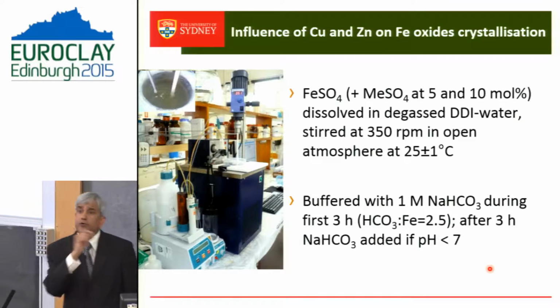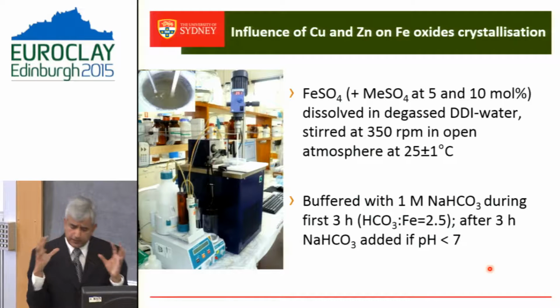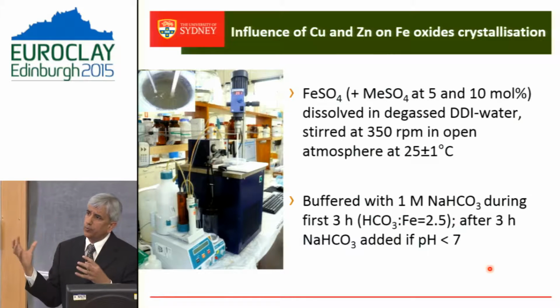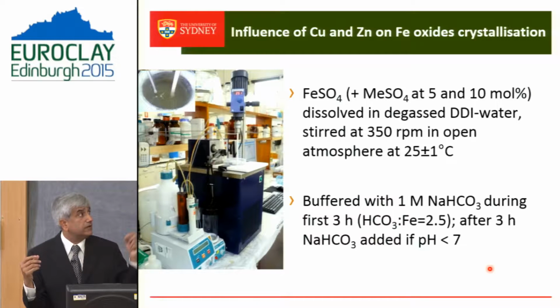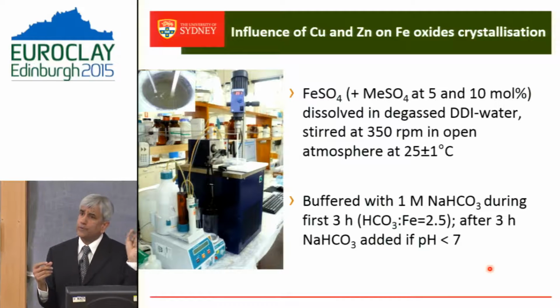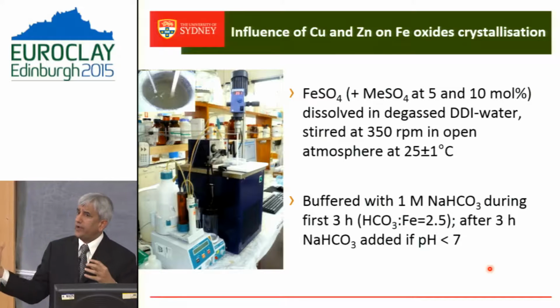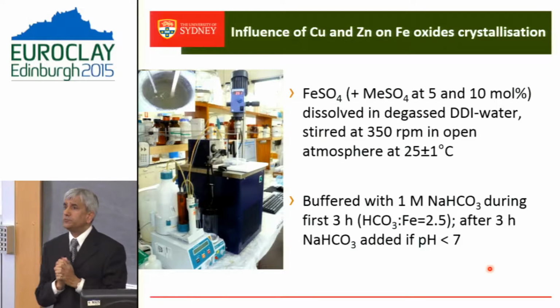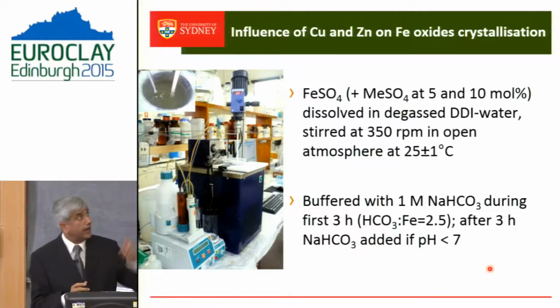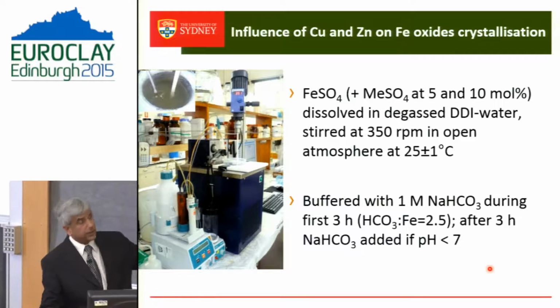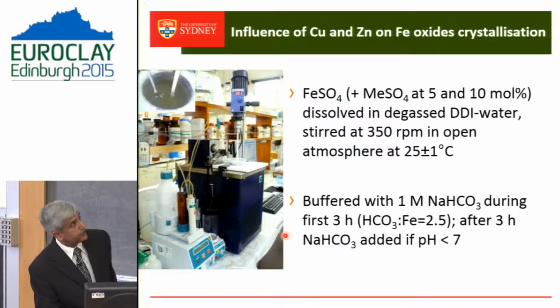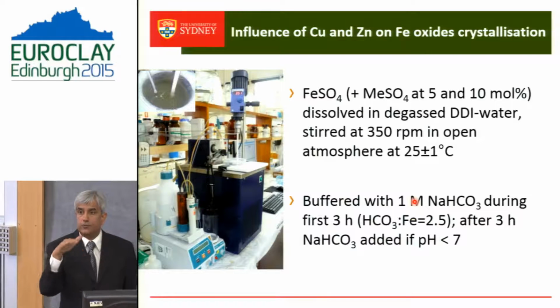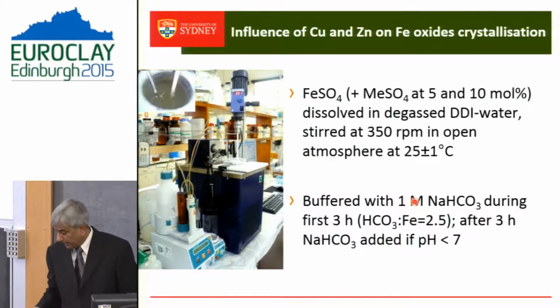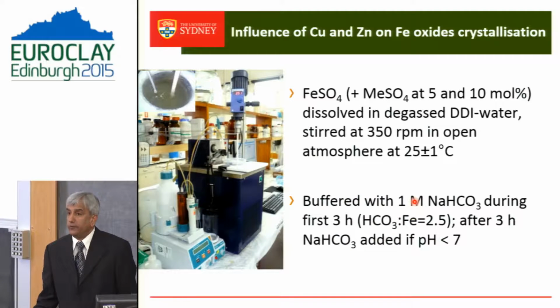One more example I want to give. We have seen that all these metals can get incorporated in the structure of goethite. But if you have those metals present in the system, they can also affect the formation of a particular species of iron oxide as well. And here, the conditions we have used for the synthesis of goethite are fairly gentle: we were maintaining the pH around 7, buffering with sodium bicarbonate in the presence of copper and zinc.